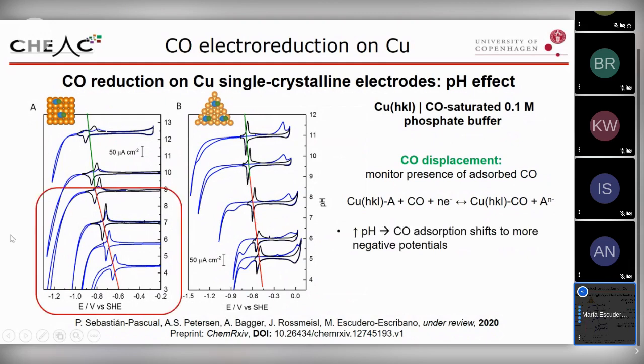So what we can see is that pH has a strong effect, and we can also see that as the pH increases, the CO adsorption shifts to more negative potentials, and we can also see two different potential regions.